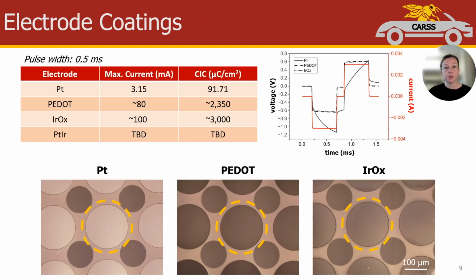For the stimulation use case, the charge injection capacity, or CIC, is a crucial indicator of device performance in vivo, as it tells us the maximum current we can safely apply during stimulation without damaging the electrodes. The CIC is measured using voltage transient measurements, in which a current pulse is injected and the resulting voltage response of the electrode is measured. This is represented in the graph in the top right corner, where we can see the input square current pulse in red and the resulting voltage in black for different electrode surfaces.